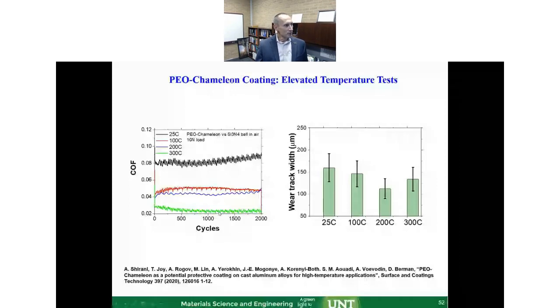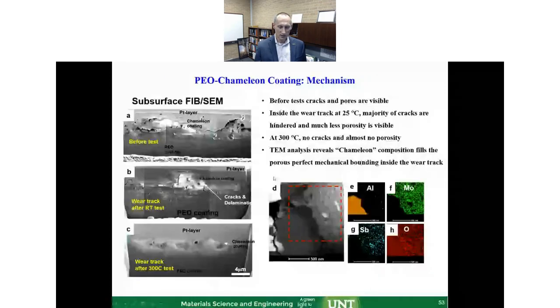So the friction is dropping very low, and we can say, okay, the friction dropped to ultra low at 300 C because we think we're driving the moisture out, and therefore that molybdenum disulfide can slide very efficiently, almost like in dry conditions. But what's happening with wear? Why is the wear so low? So to answer that, we have to go back and do some cross-section analysis with the TEM.